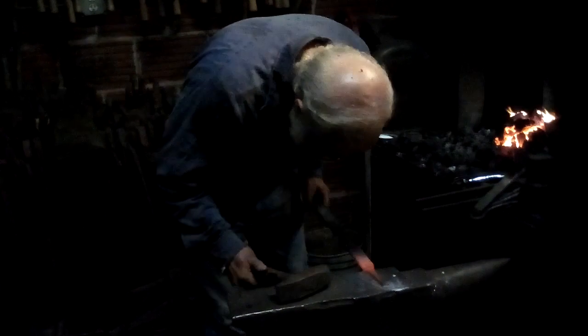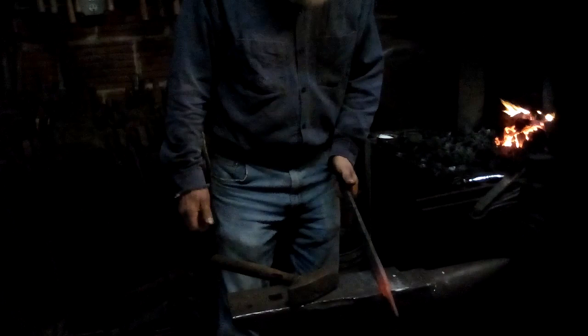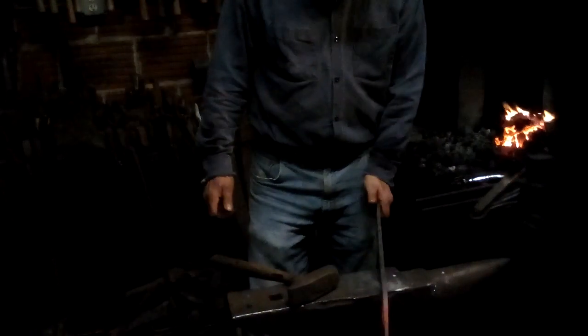Alright, that's the tang. Now I work my way up a little bit. What I am going to end up with is about a 7-inch long blade, but I have to start out by making that a lot narrower. What I'm shooting for is about 7/8 of an inch wide and about 1/4 of an inch thick, and probably about 5 inches long to forge out a 7-inch long blade. The blade will end up about 1 1/8 inch wide once I forge in the bevel.